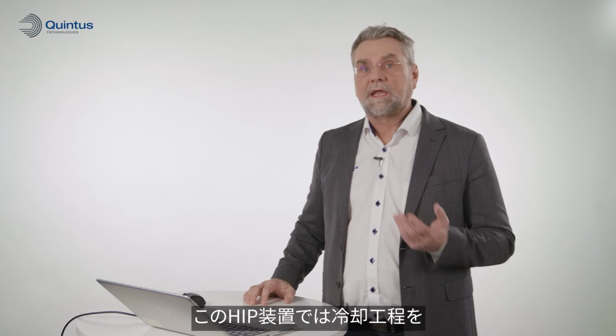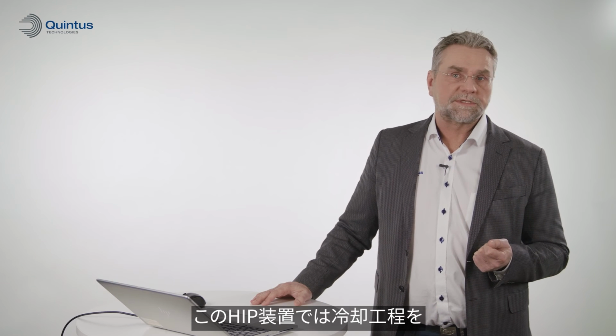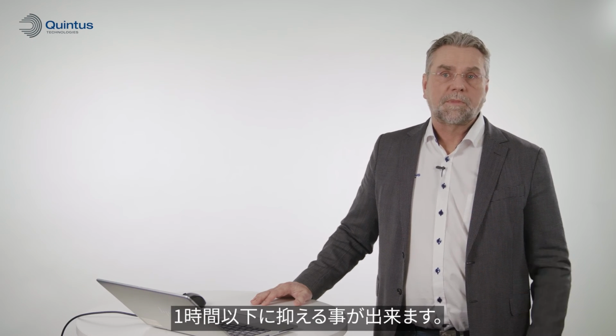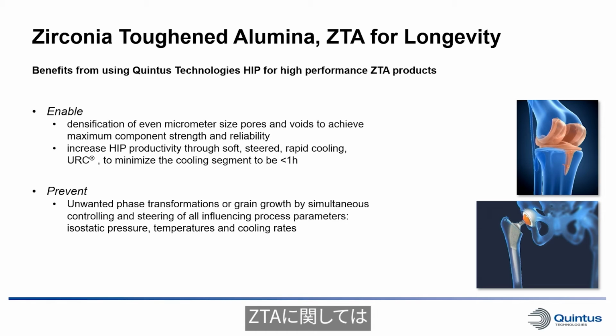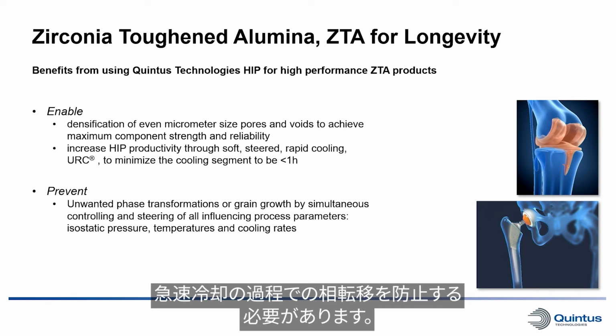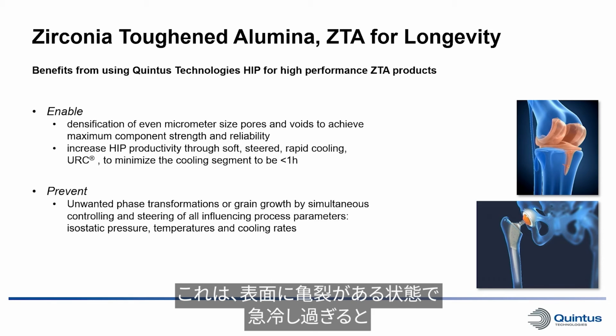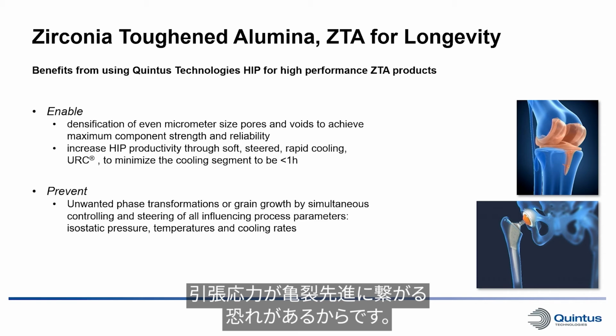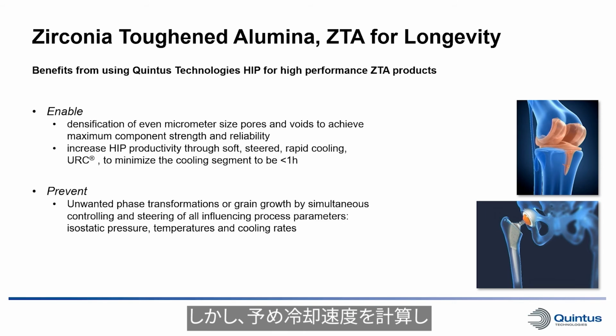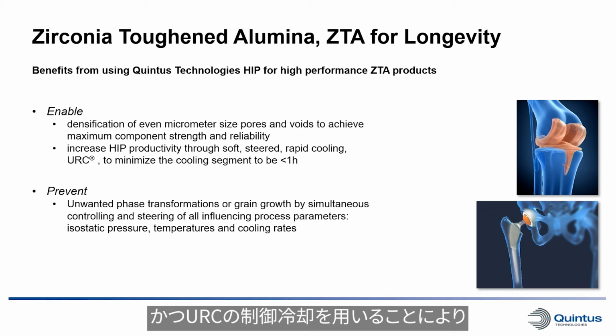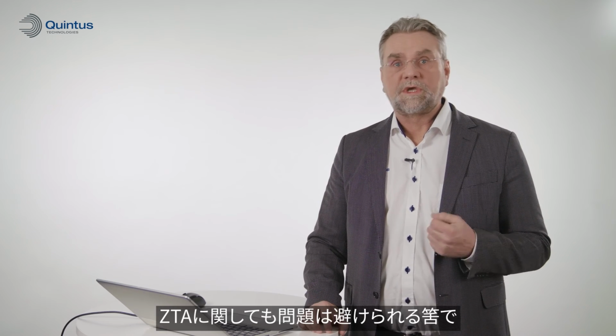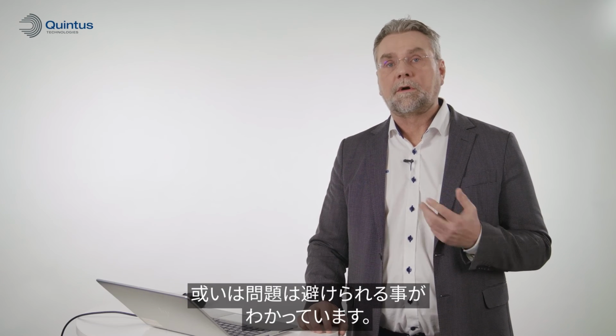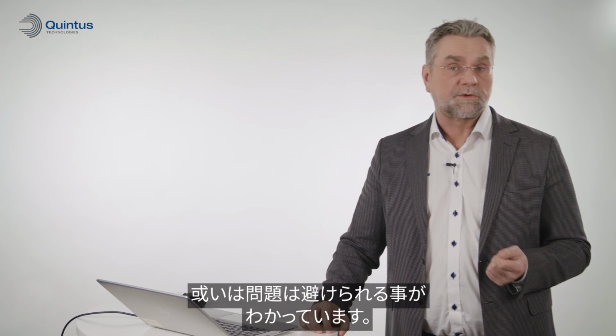And we see that we can have cooling segments also in these HIP cycles of 1 hour or less. So when it comes to ZTA, of course, we need to prevent phase transformations taking place during a fast cooling. And this could be the case if we have surface cracks and we cool too fast, bringing tensional stresses to the crack tips. But of course, if we have calculated the cooling rate and we are using the steered cooling of the URC, we should be fine also for ZTA, or we know that we will be fine also with ZTA.